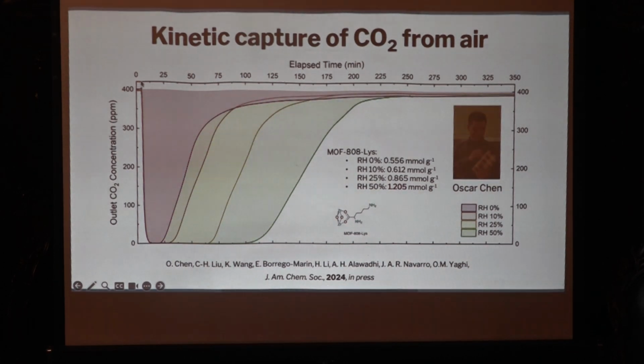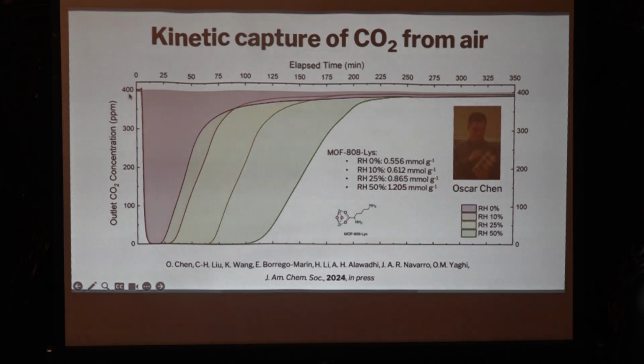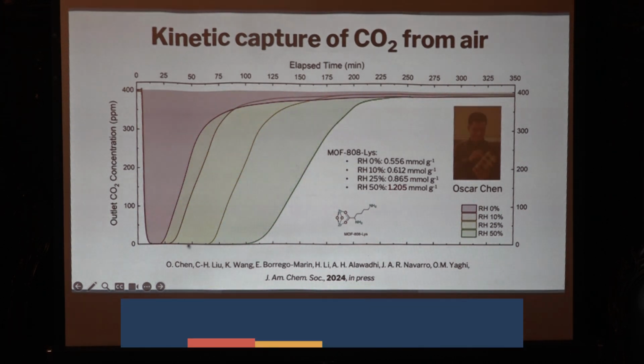And sure enough, the material over here is exposed to 400 ppm of CO2. That's how much CO2 is in the air. And immediately upon exposure of the material to CO2, the amount of CO2 drops down to zero. That means it sucked the CO2 out of the air and stays in there until the pores are filled, until all those amines have CO2 on them and saturated, and then CO2 breaks back out from the pores, okay? This area here is where the CO2 is retained in the pores. You've separated CO2 from air.